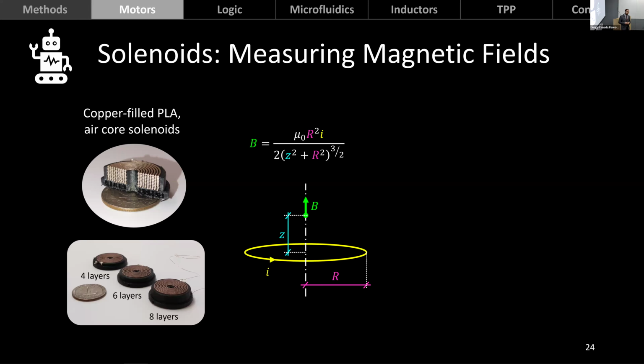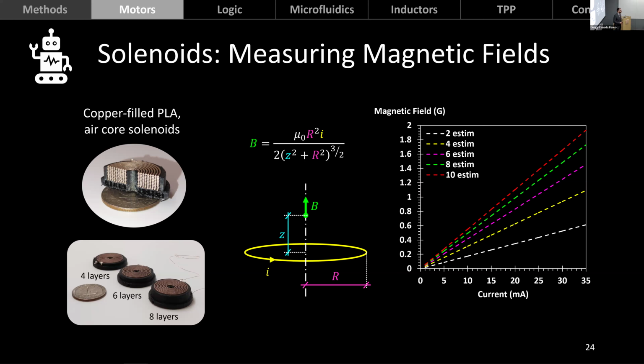Now, the first thing we did was we estimated the magnetic fields that we were expecting to see generated by these solenoids using this equation that computes the magnetic field generated by a loop of current along its axis at a certain distance. So we approximated all of the loops in these spirals by circles, and we added up all of their contributions. And these are the estimates that we got from that calculation. And then these are the measurements that we took. So as you can see, they are in very good agreement. And they're also consistent, so we're getting what we would expect.